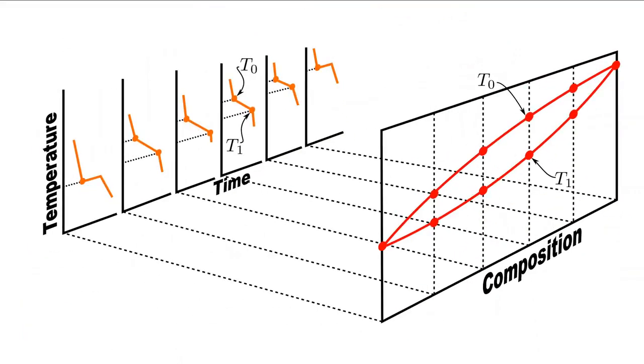Let's first start with the rate at which alloys solidify. I have plotted both a binary phase diagram and cooling curves that are typical of each of the freezing ranges presented. The temperature marking the start of solidification for an intermediate composition, i.e. one that's not a pure metal, is identified by T0 and the end by T1. Moving from left to right across the phase diagram, one has a cooling curve which is typical of the pure metal with a lower melting temperature at one extreme, and the higher melting temperature at the other. Under equilibrium conditions, the start of solidification occurs at some intermediate temperature and ends at another, as identified by the liquidus and solidus. So there is clearly a compositional effect on the cooling rates for a given rate of heat removal from one of these systems.